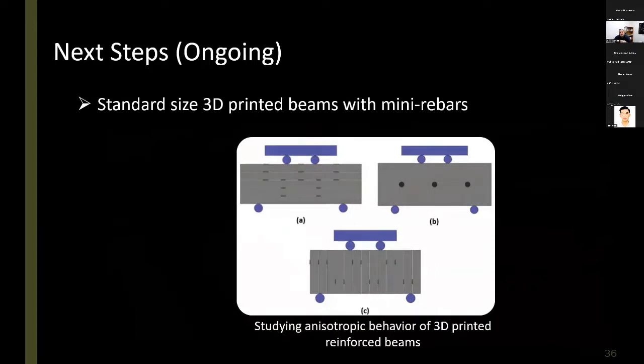And then as an additional strengthening technique to address one concern, which is the vertical reinforcement and the interlayer adhesion of these layers, we are also gonna add some mini rebars, as you can see here in the image, first manually and then with an automated system to our 3D printed beams, and try to understand and measure the improvements that we could possibly get with inclusion of mini rebars in our 3D printed beams.